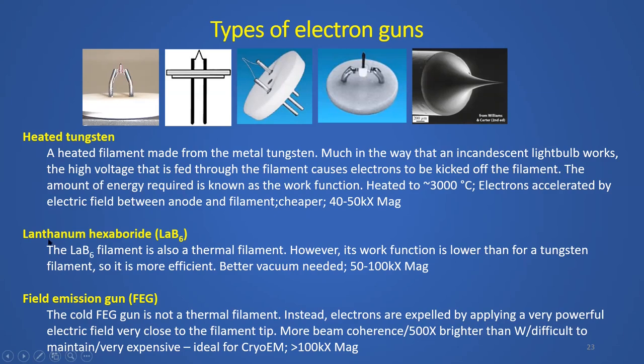And you have the second kind, which is LaB6, lanthanum hexaboride. This is also a thermal filament, but the work function is lower than for tungsten, so it's more efficient. Work function meaning that with lower energy, you can extract more electrons out of it. But a better vacuum is needed for LaB6, and it's a little more expensive than a tungsten filament.